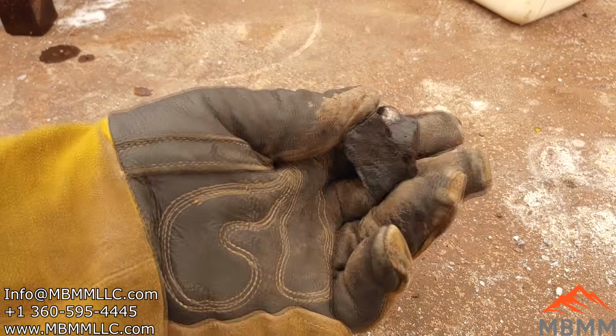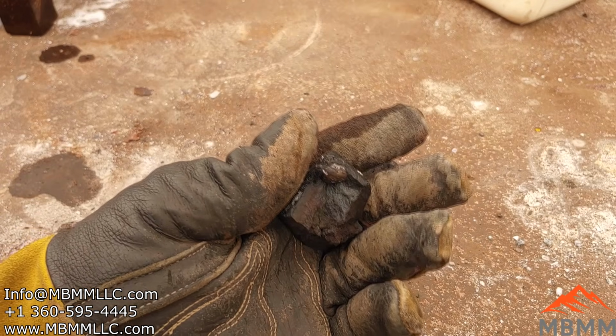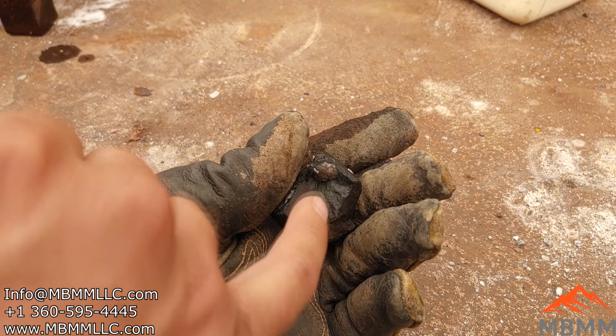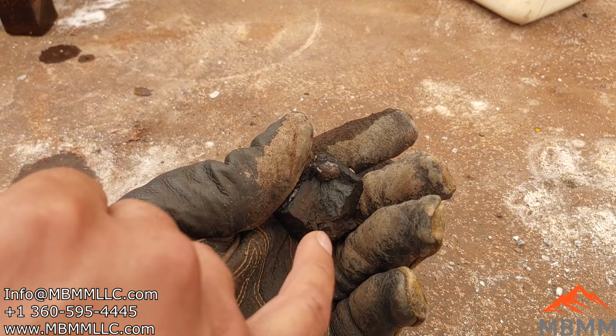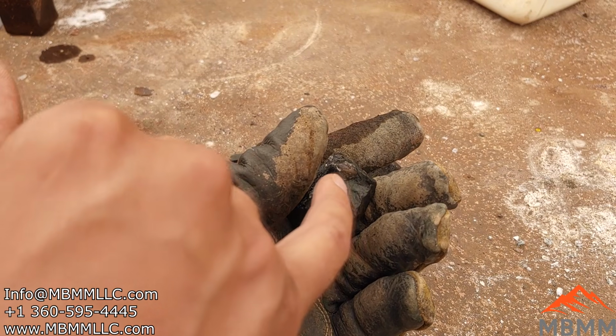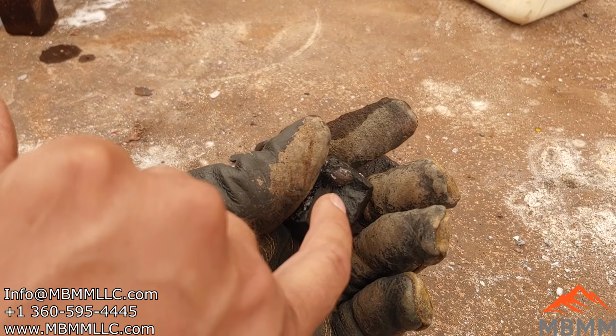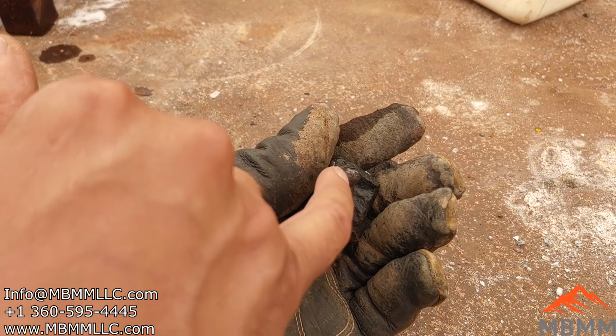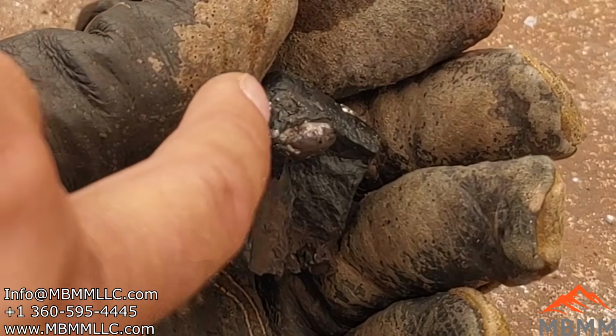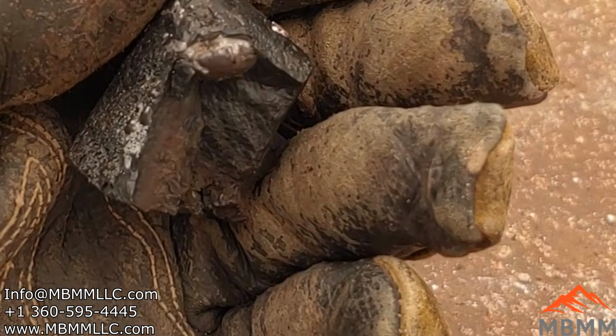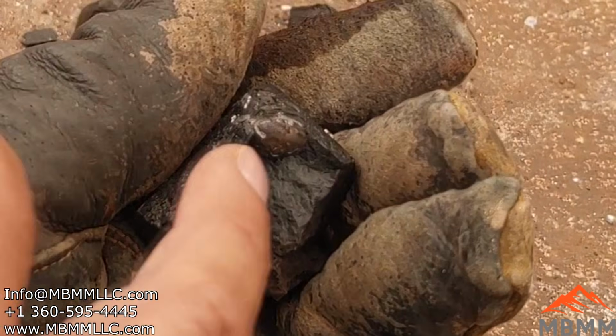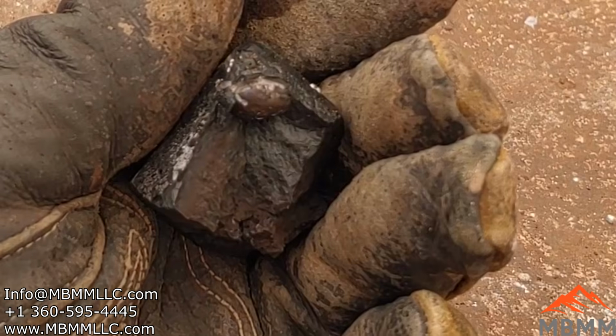All right, well, it's still hot, but there's our slag, our real basic slag. We used a lot of soda ash. It absorbed all the FeS sulfide that we made. We reduced all this lead to metal, and there's no mat. So that recipe worked really well.